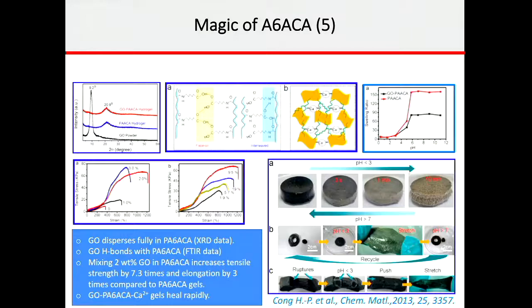Now, what is happening is that this has attracted such attention that now everybody is getting hold of A6-ACA and trying to see what better they can do. So, for example, they have taken graphene oxide and again bonded it with PA6ACA, mixing 2%, and they find the tensile strength goes up by 7.3 times, elongation by 3 times, and they heal very rapidly.